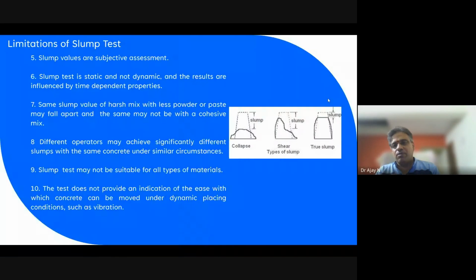How will we choose? Because practically, what will happen, we require a 125 mm slump. We order a 125 mm slump from RMC companies. So they will do it based on the traveling time and slump loss. They will do 175, then they'll reduce to 145. Like that, they come to 125 at the site. Then once they pump the concrete to the 10th story, 9th story, we are not checking the slump at the place of placement of the concrete. We assume that it is the same slump.